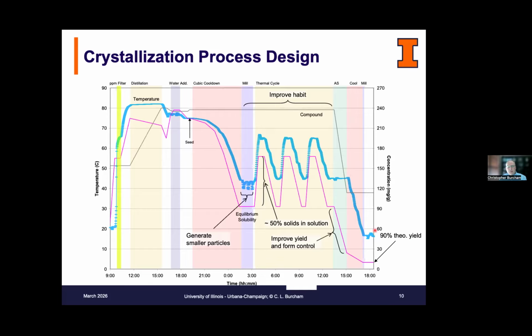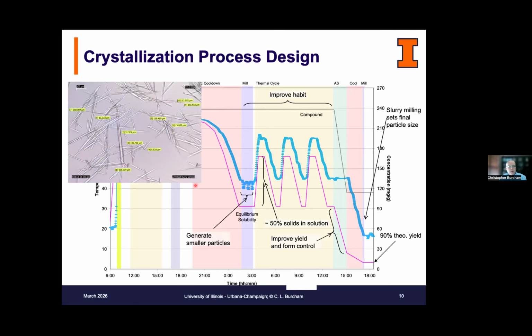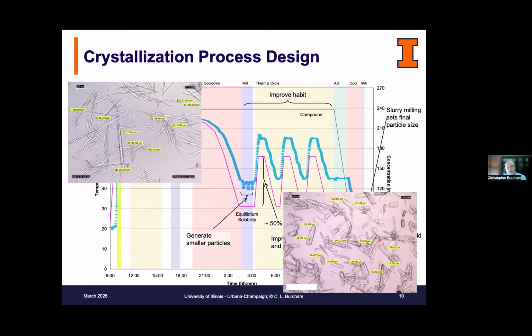And then we cooled it to increase our yield. And then at the end, we milled it yet again so that we could get a much smaller aspect ratio. In doing so, we went from crystals that looked very similar to what we had formed before the thermal cycling process to much more equant crystals. And you can see a great increase in the thickness of the crystals, as well as a decrease in the length of the crystals, and the aspect ratio being on the order of 3 to 5.